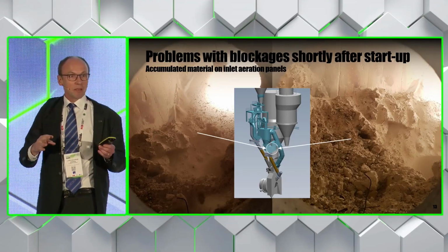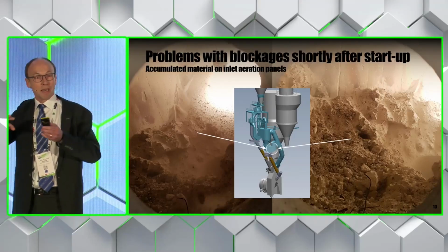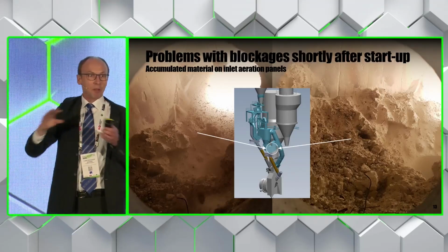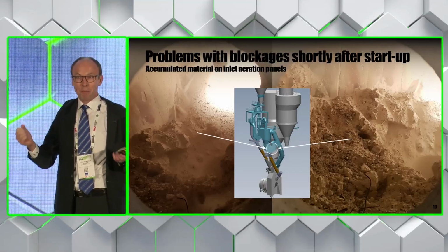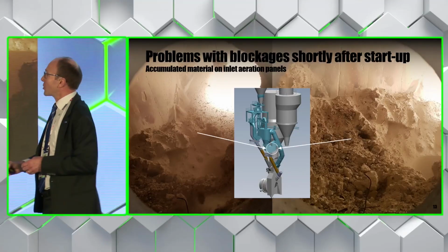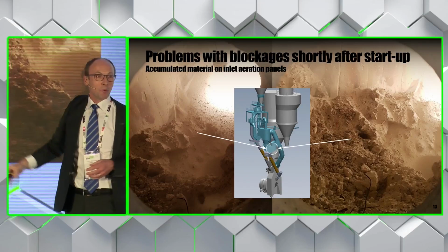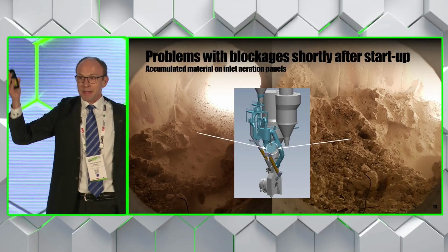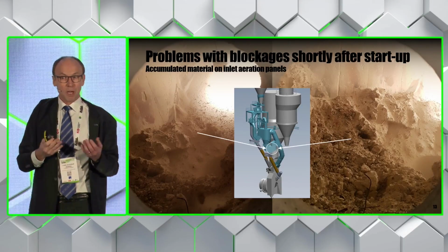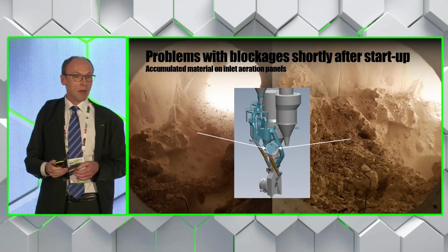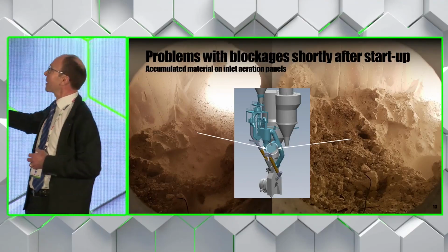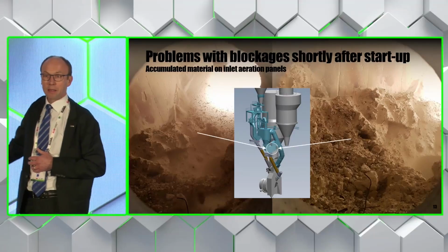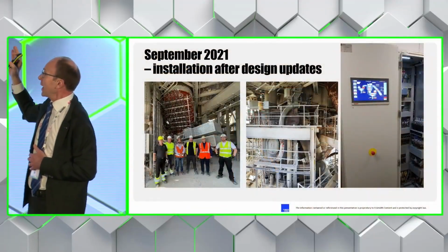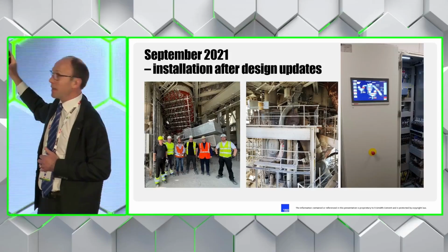And then when you stop the aeration, if any of you have had blocked cyclones and leave it blocked for a while, you'll know that everything consolidates to one big lump, which is difficult to take out. So we had quite a battle with that, and we needed to reconsider the whole design of our aeration system for this pulsed aeration and the bottom of the pyrolyzer. So basically, we rebuilt the whole bottom part of the pyrolyzer,